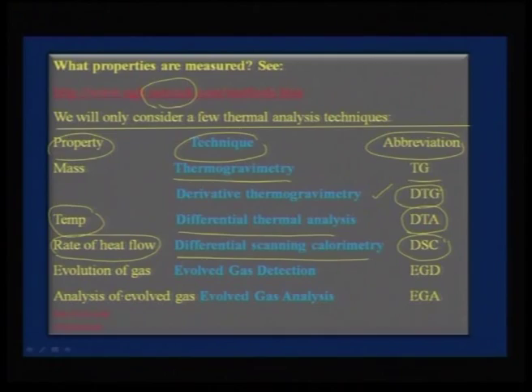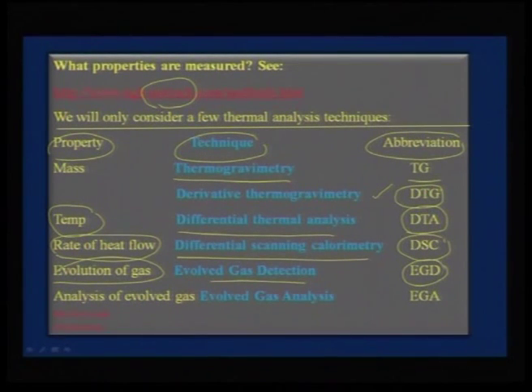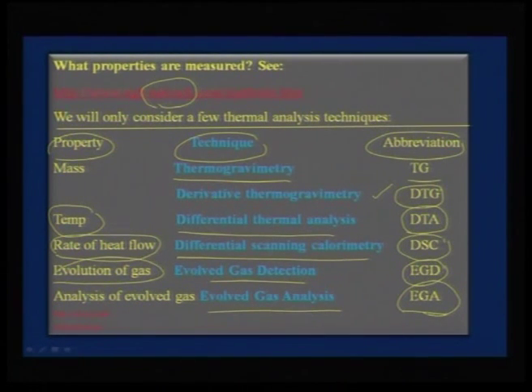Sometimes we miss out on very important mechanistic issues if we let go some of the gases coming out of the process. In such cases, it is useful to have a TGA instrument and trap the gases in a sealed tube, which can then be mounted into an infrared spectrophotometer. This gives you exactly the detail of what gases are coming out — it is called evolved gas detection or evolved gas analysis.